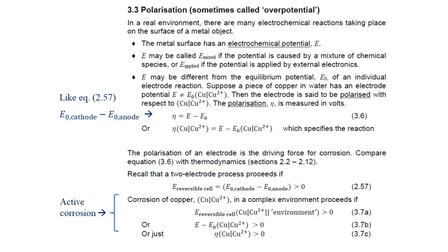We could be specific about which electrode process we're measuring the polarization of by adding the electrode notation. So then it would be eta of the copper/copper 2+ electrode is equal to E minus the E subscript 0 of the copper to copper 2+ electrode. Polarization, this eta, is the driving force for corrosion.